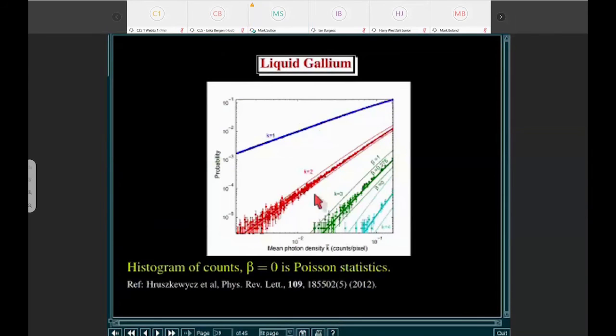Here's an example where we didn't have the X-ray beam splitter working. It turns out to split an X-ray beam, especially at 10 and 20 keV, is very difficult, and we're working on techniques to do that currently. Here, we basically looked at the scattering off of liquid gallium and measured the coherence. It's a little tricky to measure the coherence because we don't want to use the full amount of X-rays because that'll heat up our sample.